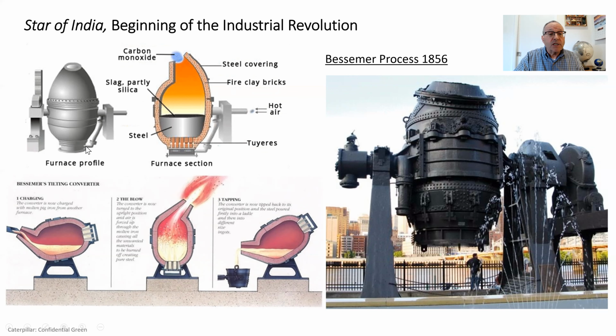And what he did is he had these big teardrop-shaped vessels that had what we call tuyeres, or pipes, down in the bottom of this pot, and they pour molten cast iron into this, and they blow air and gases up through to boil off through the liquid iron and reduce the carbon. So if you look at the process, they tilted it, they poured in this liquid cast iron, they tipped it back up, and they blow it off. In other words, drive air and gases up through it. It was a very aggressive process to blow down the carbon. And they very quickly have this low carbon steel that they could pour off, cool down, solidify, and forge.